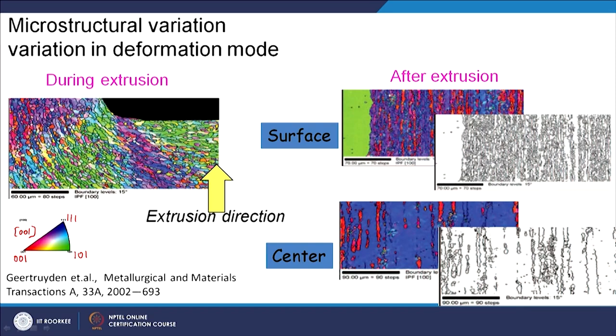So, the extrusion direction is shown here by the arrow. And you can see at this point you have very high values of strain, and then somewhere here. I am not sure about the strain values because they are not shown here, but what you can see very nicely is how the orientation is changing. There are different zones of orientations. So, basically the texture is changing during the deformation process.